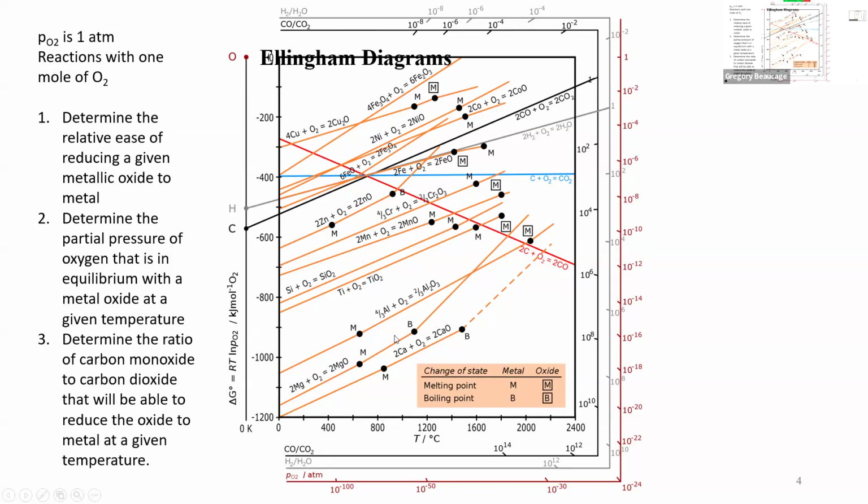There's something called magnesiothermal reduction. Magnesium is down at the bottom here, so it's the hardest to reduce. Calcium would be better, but magnesium's the one people use. It's used for magnesiothermal reduction of titania to make titanium, or of silica to make silicon. Say you could make a silica that had a certain structure that you wanted, but to make it functional, like in a battery electrode, you'd want silicon. So you'd make your structure in silica, which is easy to do.